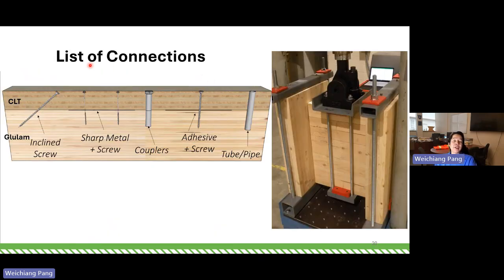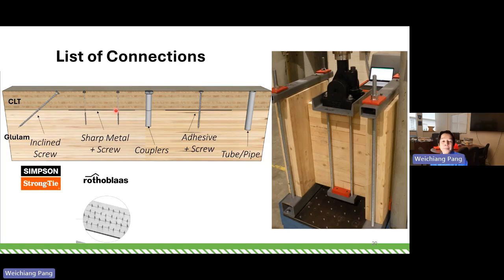This shows a list of all the connections we tested. We tested different screws, just simply the screw without any adhesive or sharp metal, at an incline of 30 degrees, 45 degrees, and some without incline, that means just 90 degrees. We also tested a sharp metal plate in between the CLT panel and glulam beam, with screws using the Rothoblaas sharp metal plate and screw.